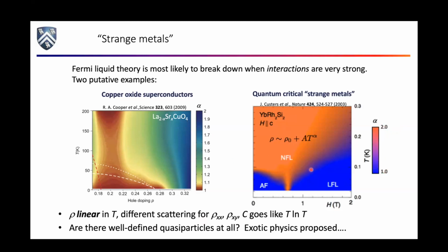The point is that there's a broad region of temperature versus some tuning parameter, in this case field, in this case doping, where the power law of the resistivity is wrong, right? The resistivity goes like T instead of T squared in the low temperature limit. And also there tends to be a different scattering rate for the transverse and longitudinal pieces of resistivity. There tends to be things like logarithmic corrections to the heat capacity. So, there's all kinds of exotic things that have been put forward on the theory side involving things like AdS/CFT and fairly exotic things about whether there even are well-defined quasi-particles at all in this system.